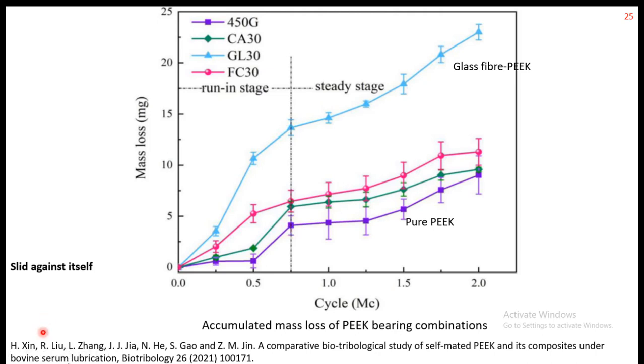And so sliding against itself, for example pure PEEK sliding against pure PEEK, and the composite sliding against composites. Here you can see that pure PEEK has got the lowest wear, as well as the carbon composite. The composite with carbon has got lower, almost close, very close to each other, but glass fiber did not work very well. So here we can learn that carbon fiber in general has done quite well.